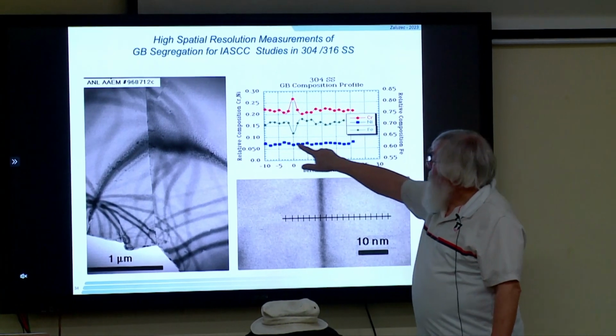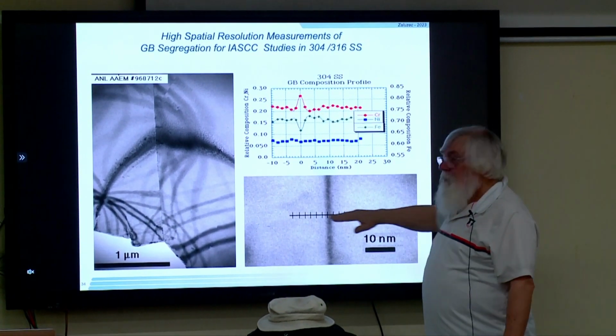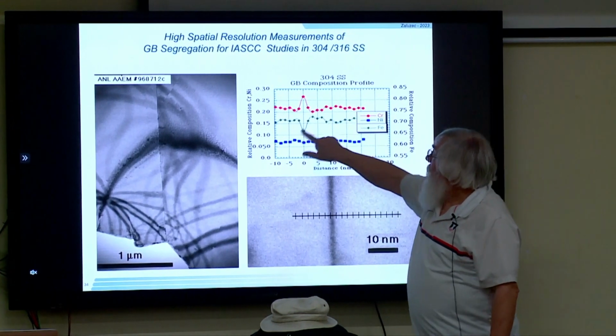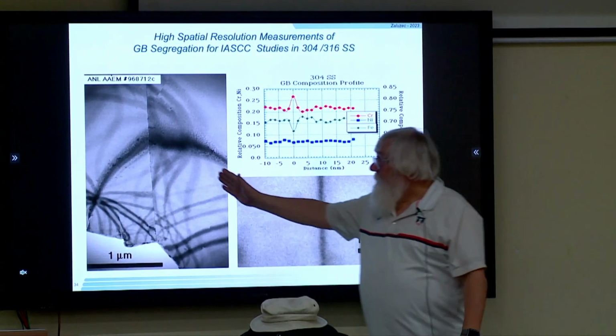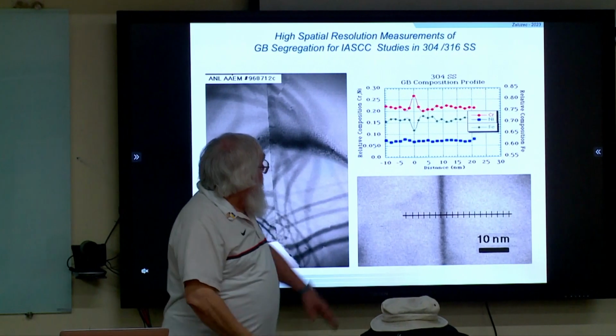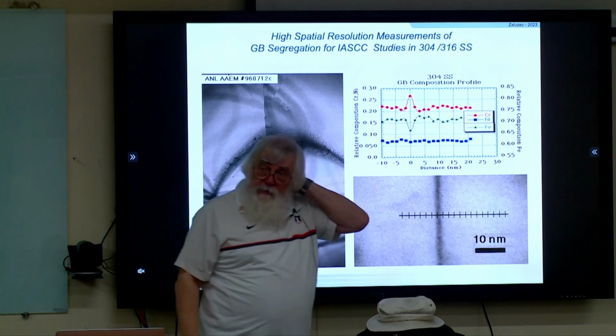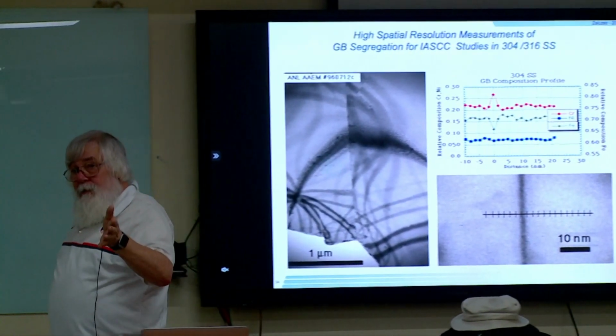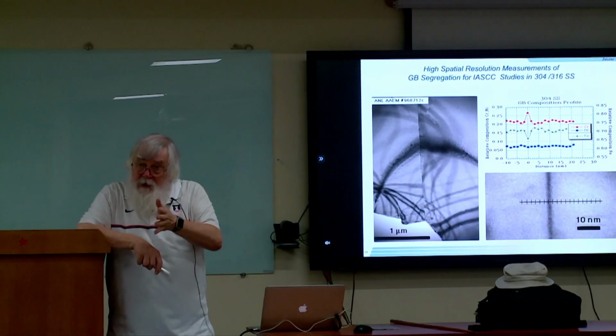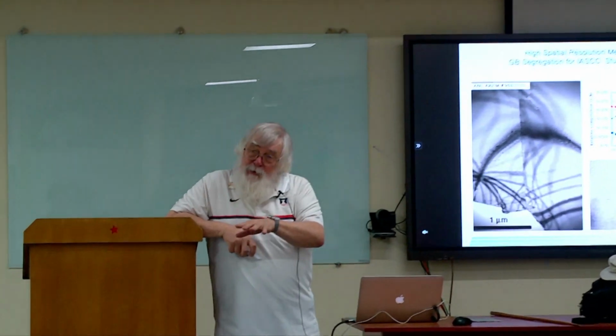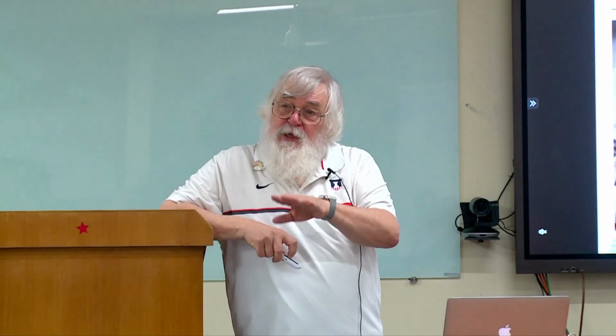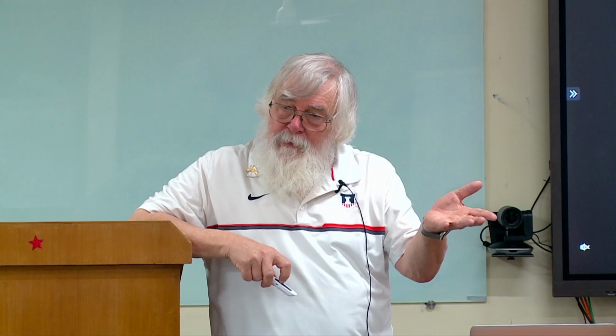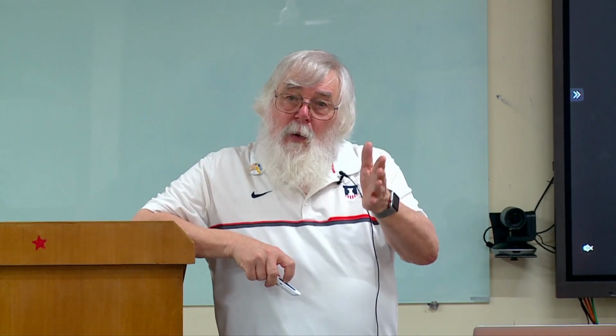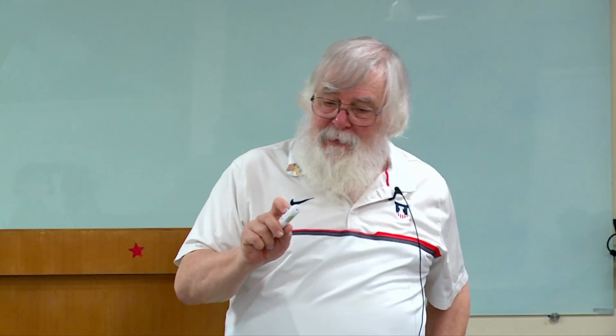If we look at this, the composition of the blue, which is the nickel, is uniform. But the composition of the iron and the chromium changes. Why is that grain boundary weaker? We've got a depletion of the iron and an increase of the chromium at that grain boundary. That's why the material fails. Now, a different question is, how do we stop that? That's part of your research project, how one determines what's causing it. First, you have to know what the problem is, cracking. Then we have to do a measurement to figure out, is there something significant about that? Yes, we got a change in the composition of the grain boundary. Then the next thing is, how do we answer that question? That's another research project, right?